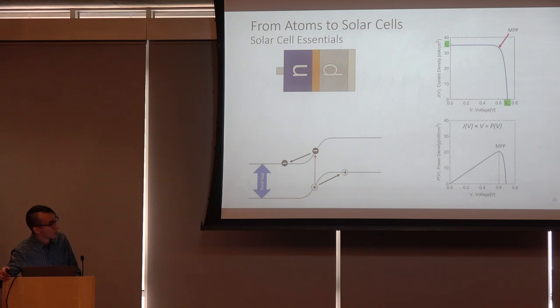Then if we look at the maximum power point, we can now draw two rectangles that look like this. The ratio in area of those two rectangles is called the fill factor. You want the fill factor to be as close to one as possible. And that one is basically a measure of how healthy your solar cell is. If the JV curve is all squashed in and not particularly square, then that means that your solar cell has some sort of serious issue.